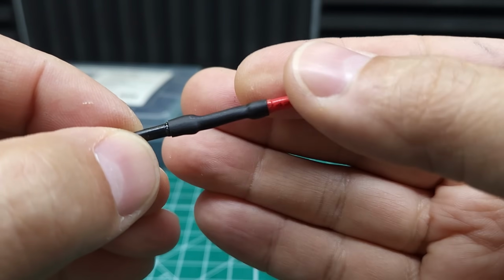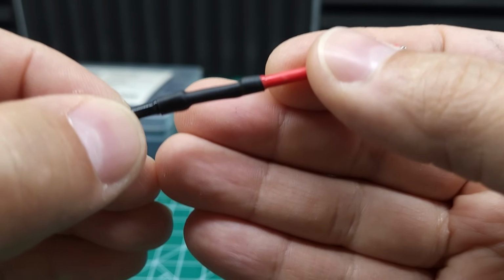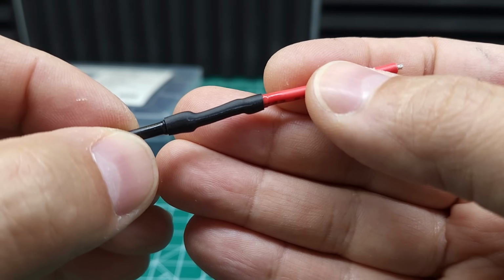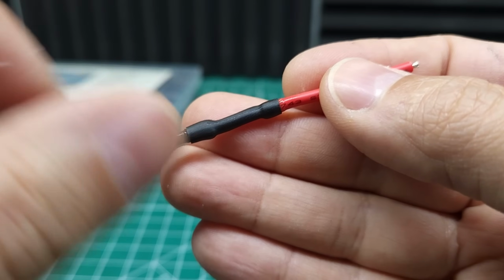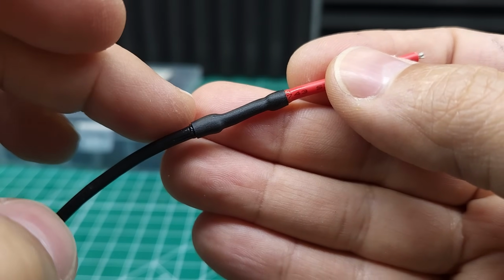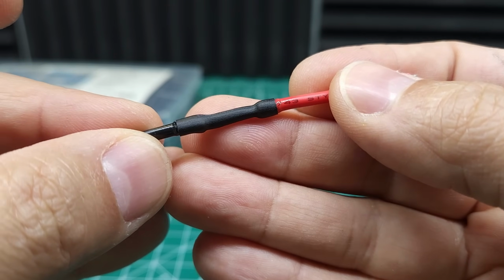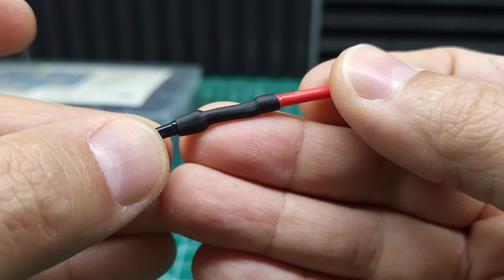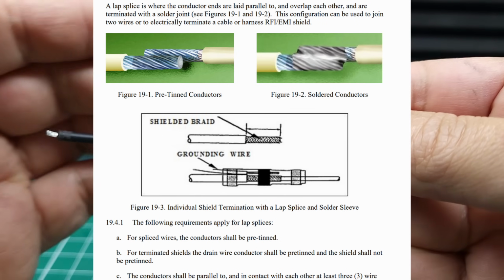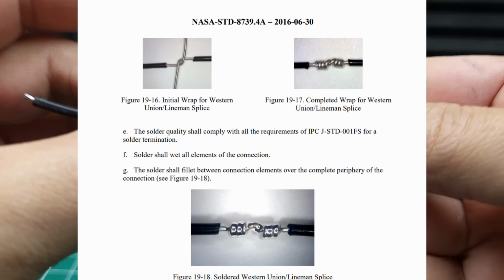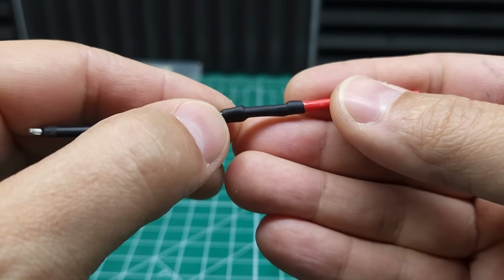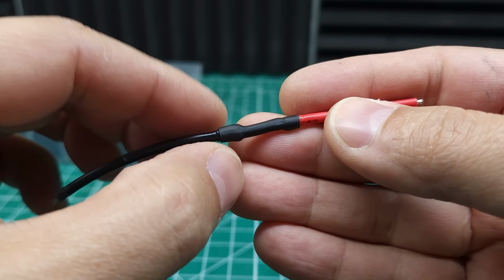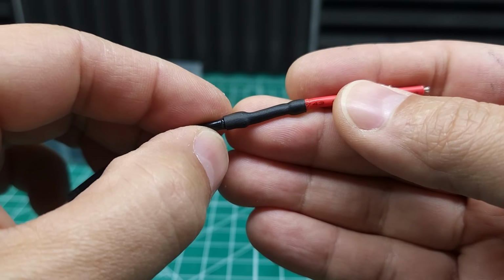Not only does that create a stronger connection than regular heat shrink, but it also creates a waterproof connection if you do it correctly. Regular heat shrink, electrical tape, and things like that can let moisture get into the connection, and that can cause corrosion to form, which can end up killing your joint in time. As you can see here, according to NASA, both the splice joint and the lineman joint are perfectly valid ways of joining wire. And if you want to learn their specifications for it, I definitely recommend Googling it because there's a ton of really good information in their paperwork.